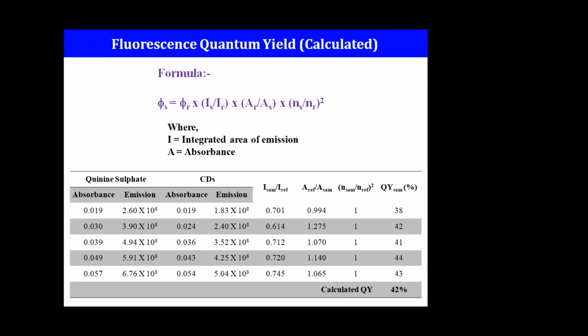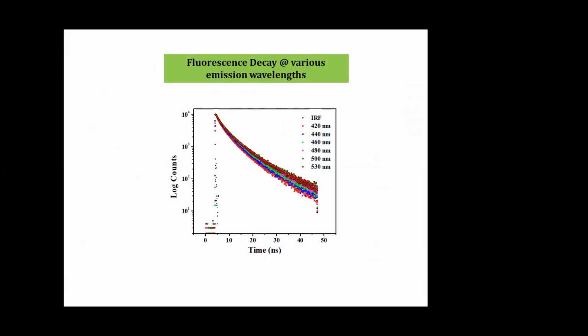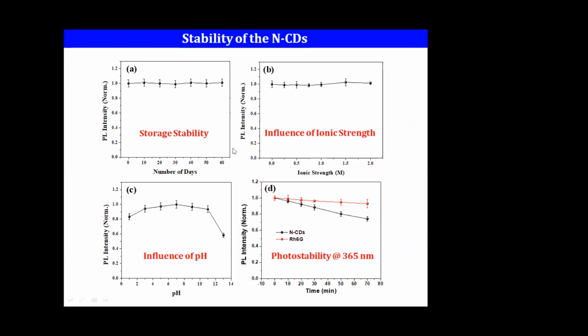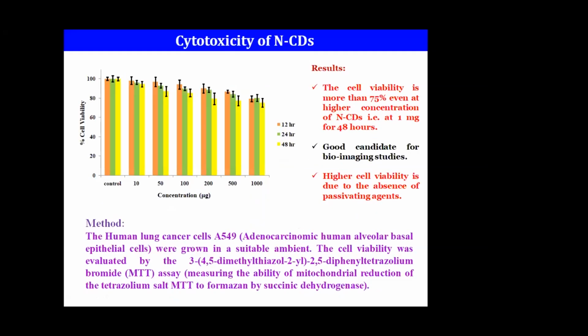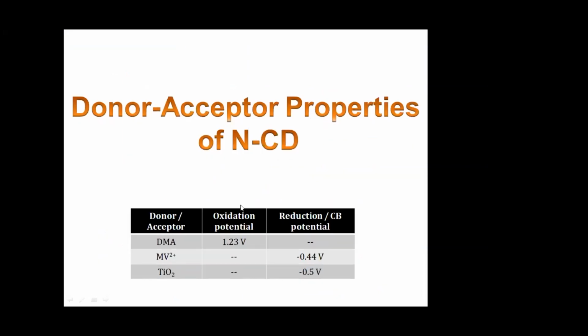We follow the quantum yield calculations by relative methods, and also analyze the fluorescence decay lifetimes at different wavelengths, and the application towards biology: stability, influence of ionic strength, photostability, pH stability. All that seems to be good, we don't see much problem. We also check the cell viability. It's a good candidate for bioimaging application also. Now we have also taken the human lung cancer cell A549, and that really works well with this material.